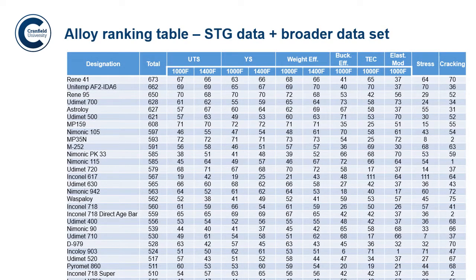So here's a ranking table. This is the broader data set, and the alloys are ranked and totals are given in this column. The top performing alloy now, and this is without considering how weldable the alloys are at the moment, is Rene 41, which is right at the top, followed by a few other alloys. Then we get to the other alloy we're interested in, which is 718, which is in the bottom middle at the moment, not looking too great. And then 188, which is the cobalt based alloy, is right off the table at the moment.